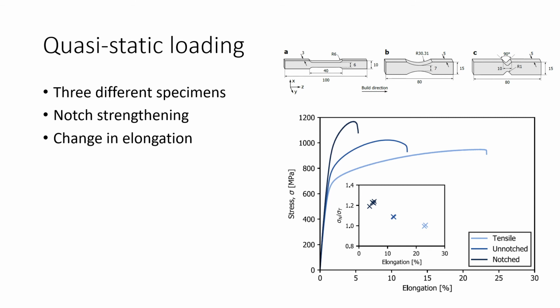And then we also did some static loading. And what we observed, we tested 3 specimens, also including one tensile specimen. And for the notched specimen, of course, we had the notch strengthening effect and the lower elongation, while for the tensile specimen we didn't have the notch strengthening effect and longer elongation.